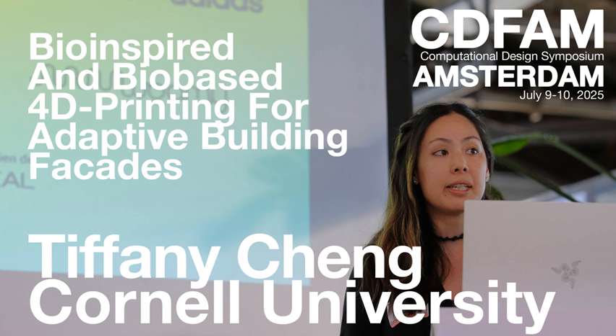So we tested the 4D printed material system that we created and evaluated the ability for it to stay gripping onto a support pole. Here you can see the pure helix mechanism gripping onto a 30 millimeter diameter pole and self-releasing after 40 minutes. I'm not sure why the videos are not working, but in comparison, the helical system without the pocket mechanisms can actually stay gripping onto even smaller diameters and stay gripping for over 3 hours during moisture uptake. Okay.